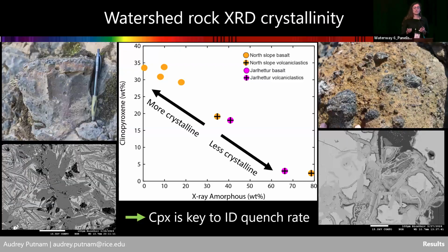And then we see these trends in the mineralogy expressed in the bulk XRD of the lithologies in the watershed. So here I'm showing clinopyroxene versus X-ray amorphous for a number of samples in this watershed. And we can see that there is a large variation in the crystallinity of these rocks between 0 and 80 weight % amorphous. And this trend also holds if we compare any one of these crystalline phases to the normalized sum of crystalline components, taking out the X-ray amorphous component. So this is not just autocorrelation.